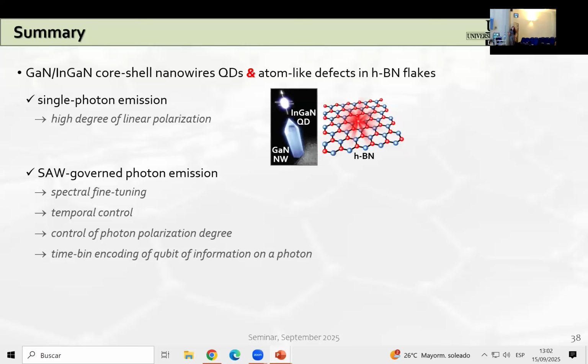And so this brings me to the summary. What I have shown here is that we can generate single photons, which are highly linearly polarized, using nitride core-shell nanowire quantum dots, and also using atomic defects in HBN flakes. We have also seen that these emitted photons are quite sensitive to propagating acoustic waves, and that this can be used to control in situ the photon emission wavelength and its emission time. We can also control the photon polarization degree and encode information by time binning.